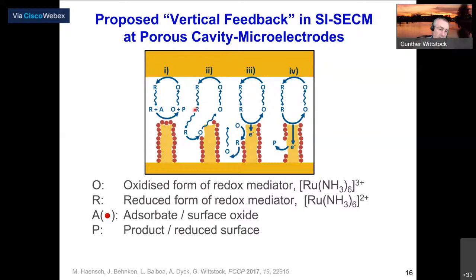So the reduced mediator may diffuse in the pore space of the nanoporous gold and titrate the surface oxides directly. But on the other hand, it may also pick up or inject an electron in the gold structures where the gold oxide has been removed. And then the electron is basically transported inside the conductive network.